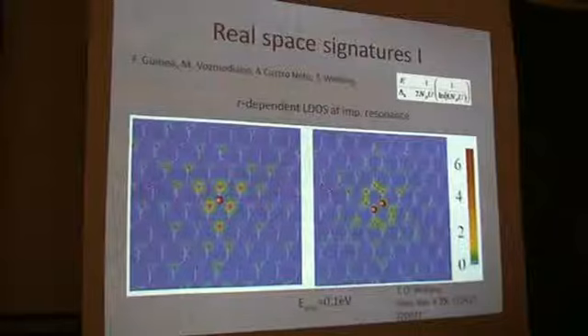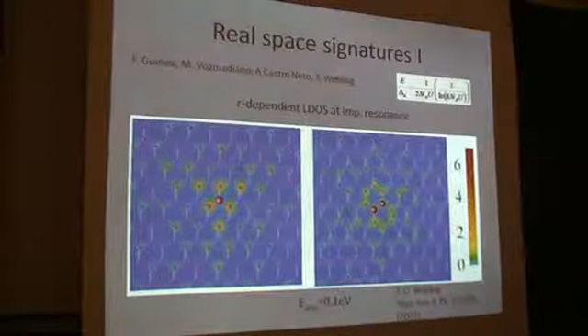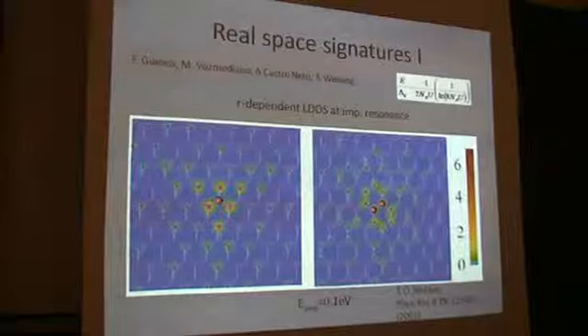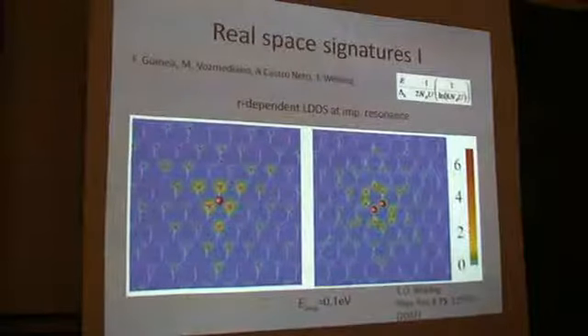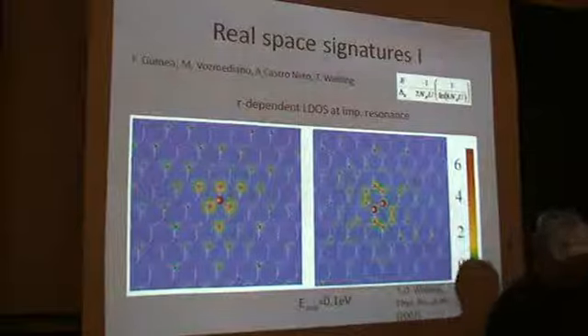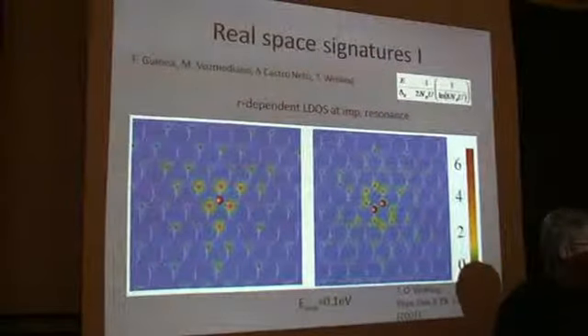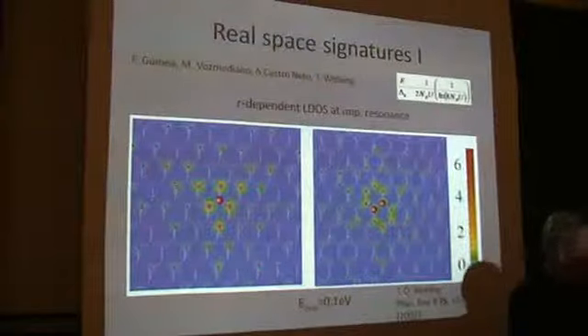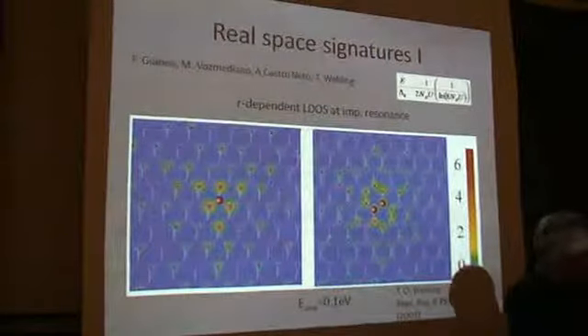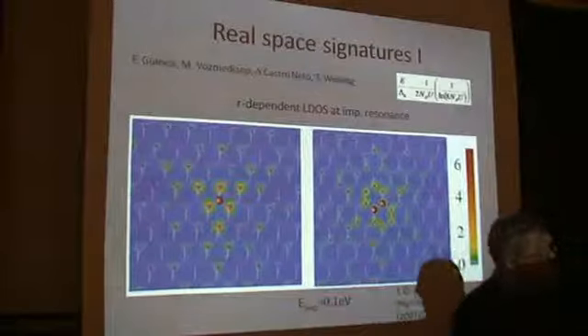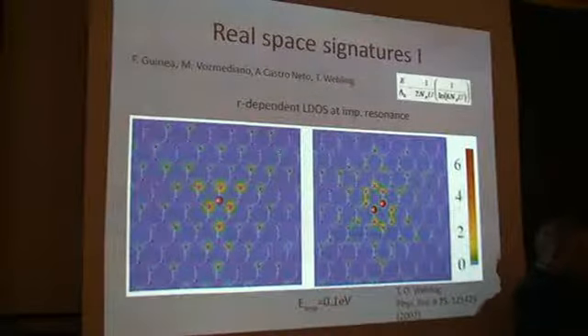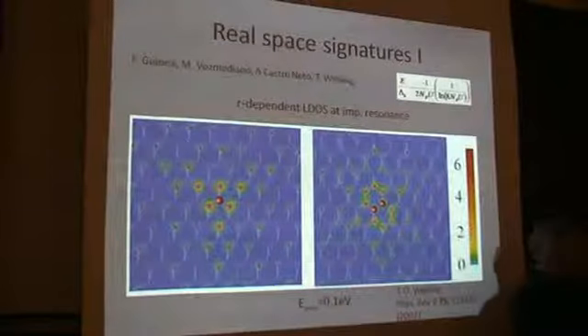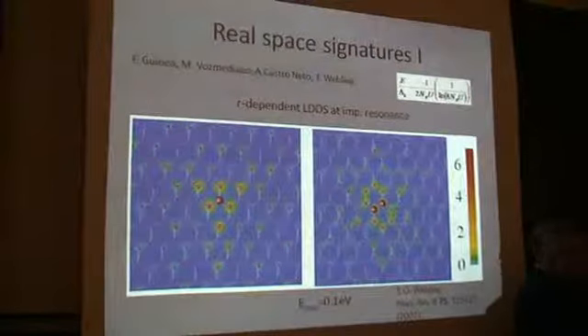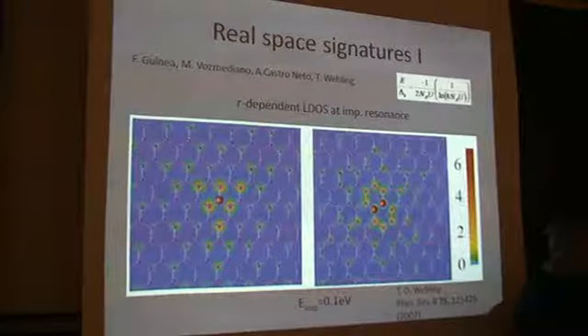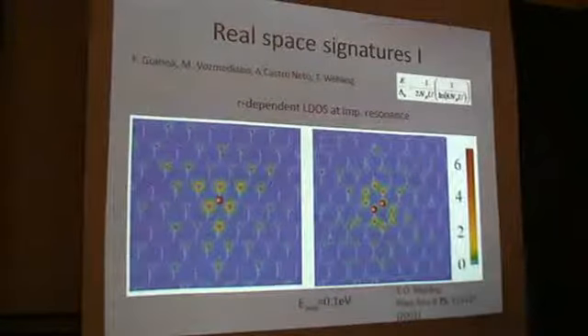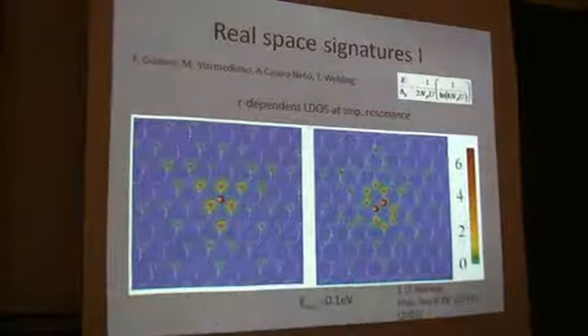So does it correspond to doped graphene? Right now I look at this problem exactly at the half-filled case, which is commensurate. Then if you move off, the beating will be slightly incommensurate compared to the lattice. Is kF non-zero? kF is 0. It's exactly at the Dirac point. It's a half-filled case. You said you have Friedel oscillations with kF. If it's 0, what does it mean? Well, it means that this is a Friedel oscillation consistent with the corner of the Brillouin zone. The point is K capital. And so when it's not kF compared to the center of the Brillouin zone, it's a full K. So if you create a wave packet sitting in one node, it still knows about the total wave vector. But then when you feel it, it will have harmonics at K capital plus or minus K Fermi. So you're considering only non-magnetic impurities?